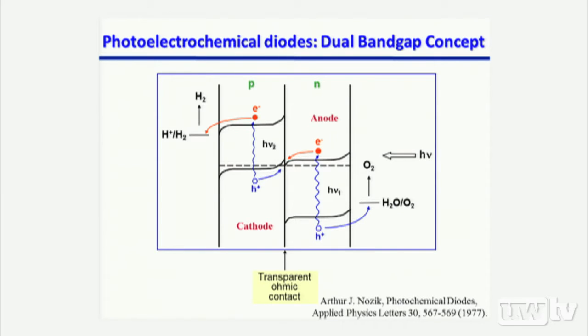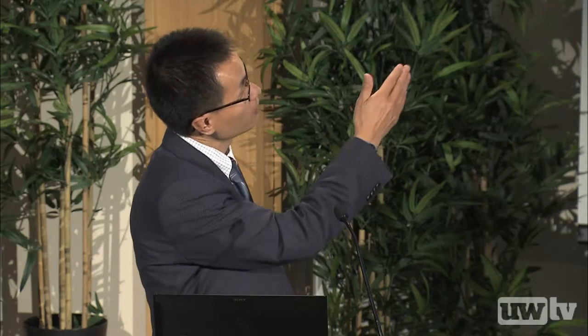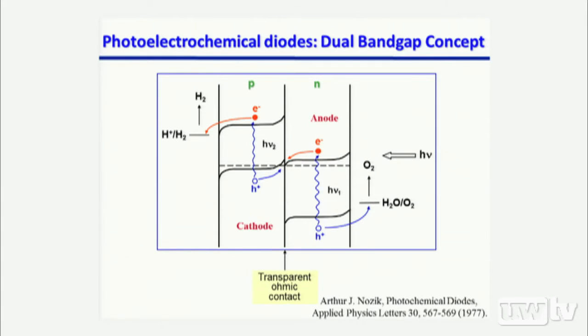And this way, the semiconductor will capture the entire solar spectrum and will drive those two half reactions. So P-type cathode, N-type anode, you dip into water, electrolyze. Then on the P-type side, the minority carrier electron will be used for the water reduction. On the N-type side, the minority carrier, which is a hole, will be used for the water oxidation. And in the middle, we need a transparent ohmic contact to make sure the majority carriers are recombined in the middle.